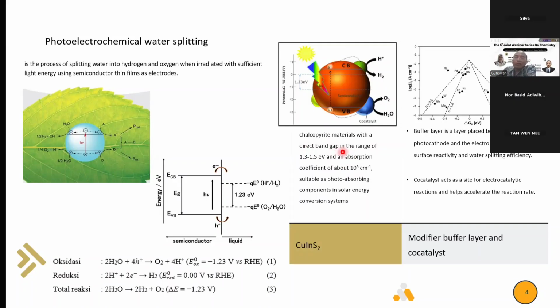So that is the outstanding property of copper indium sulfide. Also, we can use gallium to dope the copper indium sulfide, so we call that copper indium gallium sulfide or selenide as the absorber here. Here is the role of the co-catalyst. A buffer layer is a layer placed between the copper indium sulfide photocathode and the electrolyte to improve surface reactivity and water splitting efficiency. The co-catalyst acts as a site for electrocatalytic reaction, helping accelerate the reaction rate.